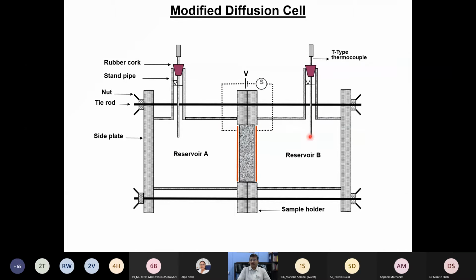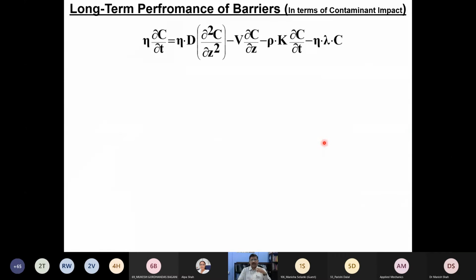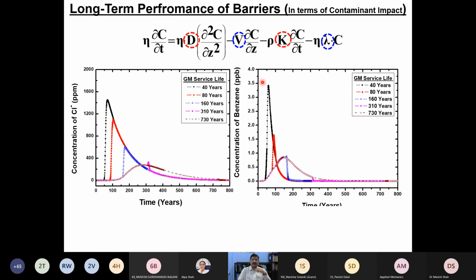We can monitor the T-type thermocouple temperature of both chambers. We maintain the leachate head more or less the same, constant across the cell. That means that the hydraulic gradient is 0. That means the contaminant migrates from source reservoir A to reservoir B only by the process called diffusion. Then by knowing this, we can back calculate this one. From the same column flow-through studies, we can measure the advective velocity. That means that we know the diffusion term from the diffusion test. We know the term K is a partition coefficient or distribution coefficient. People will use different terminology, depending on the type of isotherm you use. And we know the decay coefficient of a given contaminant if it is an organic contaminant.